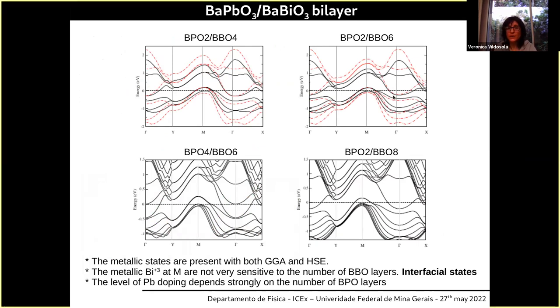Here is the band structure of different sizes, and we observe in red the hybrid functional calculation, and in black the GGA calculation, because for the larger system we were not able to calculate with the hybrid functional. We have to be confident that the metallization was not an artifact of the GGA, and we see that even the hybrid functional, which is able to describe properly the band gap of the material in bulk, also shows these 2D metallic states for these bands.